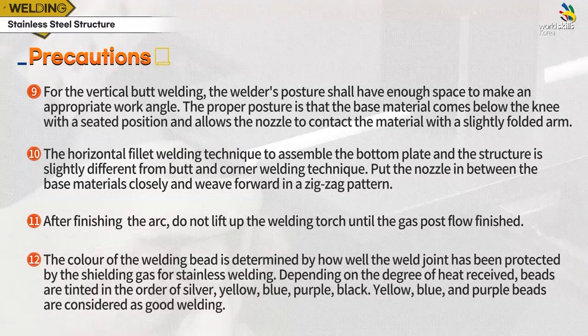The color of the welding bead is determined by how well the weld joint has been protected by the shielding gas for stainless welding. Depending on the degree of heat received, beads are tinted in the order of silver, yellow, blue, purple, black. Yellow, blue, and purple beads are considered good welding.